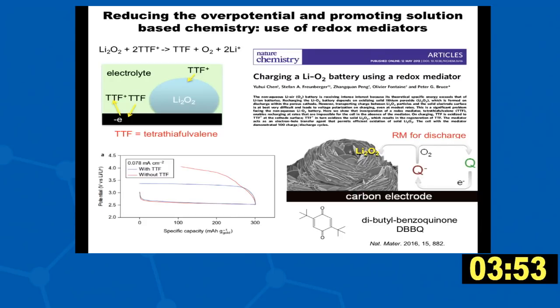The other thing that we want to do is to try and increase the solution-based mechanism, and in order to do that, we use a redox mediator. So these were pioneered by a number of groups, notably John Owen's group on using redox mediators for discharge. Peter Bruce's group were the first to come up with a redox mediator for charge. And let me illustrate what that means.